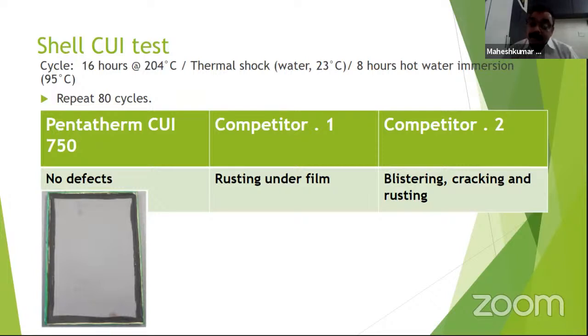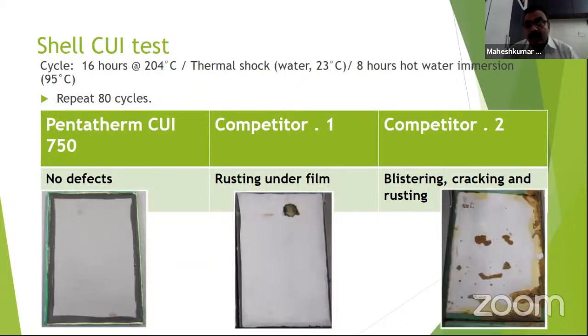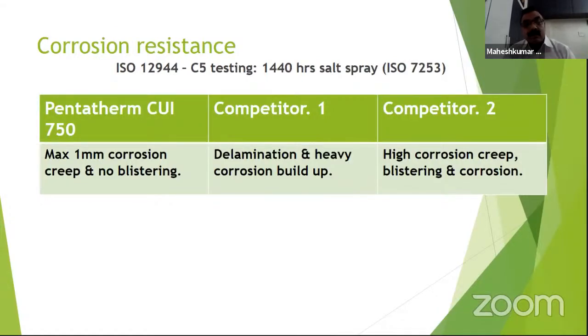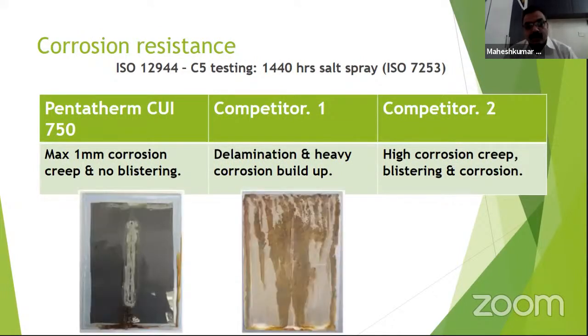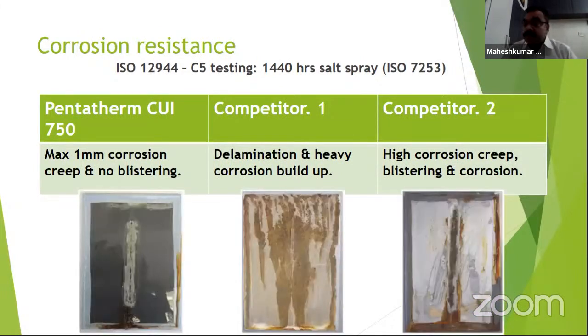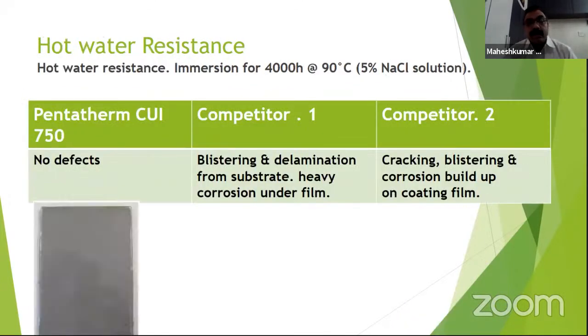It was the repeat cycle of more than 80 cycles. We have tested our Pentatherm CUI and found it gives maximum resistance to all the CUI tests as per the Shell specification. Corrosion resistance: what we found was a maximum of 1 mm creep. Delamination, which was observed in other coatings, was very high. Then we also tried the hot water resistance at 4,000 hours at 95 degrees C.